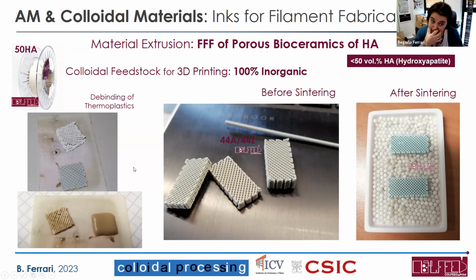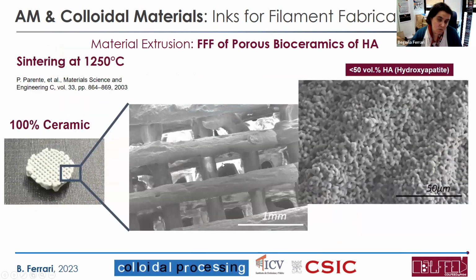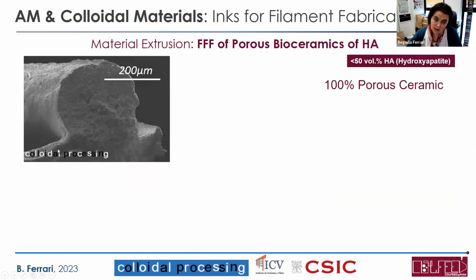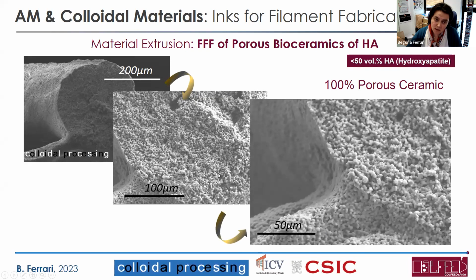And we can try to debind it. That is not so easy sometimes. And sinter our material, right? This is the structure of it, full hydroxyapatite, right? So we can do that with hydroxyapatite, and we can achieve a very nice porous structure inside of the filament, and also very good joining between layers of the scaffold, right?